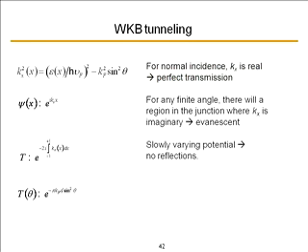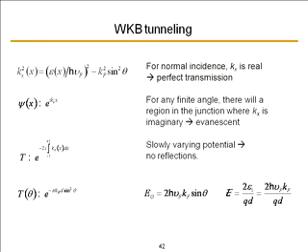All right, and you do the algebra, and it's in one of the references that we have, and the result you get is that the transmission probability is e to the minus pi kF d, where d is the width of this transition region, times sine squared theta. Okay. Now, if you want to, you can recast it into a different form so it might look like something you may have seen before.